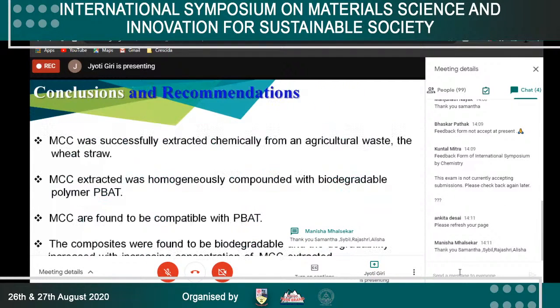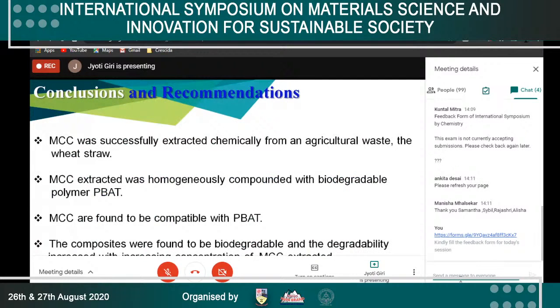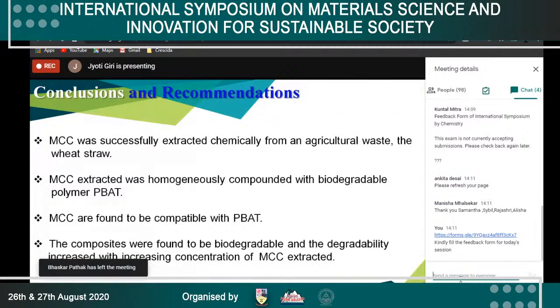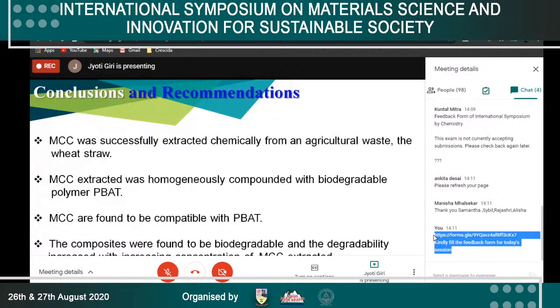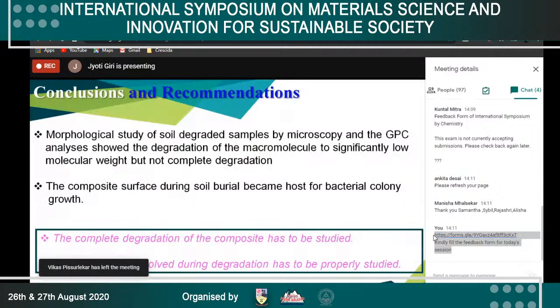This work shows successful extraction of MCC from wheat straw to compound with the biodegradable polymer PBAT, and we observed degradation susceptibility parameters such as water absorption increasing and contact angle value decreasing with the MCC content, and GPC data also showed decreasing molecular weight of PBAT with increasing compost period and increasing MCC content. Still, a few works remain to observe complete degradation and the mechanism involved in it.